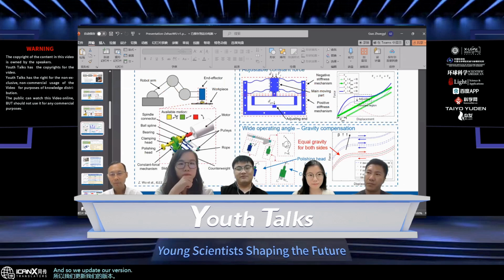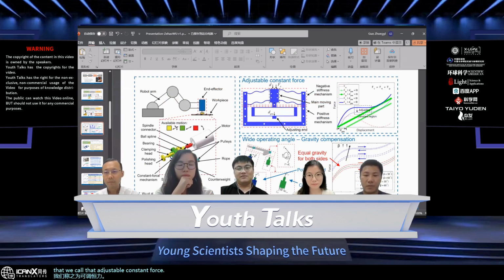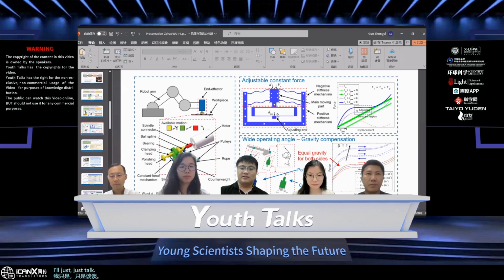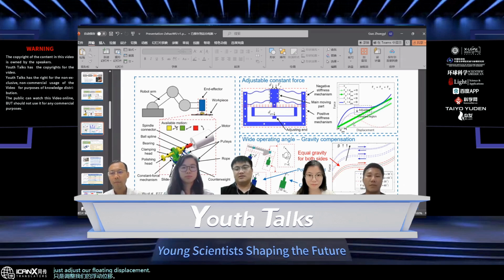And so we updated our version, which we call adjustable constant force. When we adjust the preloading displacement of the fixed end of the positive stiffness mechanism, the force displacement curve of the positive stiffness mechanism will shift, and then the force can be adjusted. So with different polishing tasks requiring different polishing force, we can just adjust our preloading displacement so that we can obtain our expected polishing force.